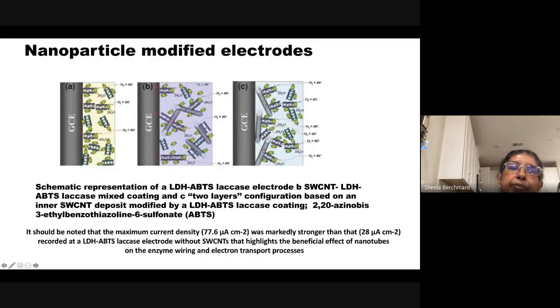Other types of nanoparticles that are being used in enzymatic fuel cells are clay nanoparticles, also layered double hydroxide. This example shows the layered double hydroxide can immobilize both CNT as well as the enzyme molecules, so that direct electron transfer can be observed. Here, in both the cathode and the anode, layered double hydroxide is used along with the mediator ABTS. ABTS is 2,2-azino-bis 3-ethylbenzothiazoline-6-sulfonate. This is a mediator, and it is used along with the laccase to produce direct electron transfer, and the maximum current density observed in this case is 77.6, which is higher than 28 microamperes, which is observed without CNTs.